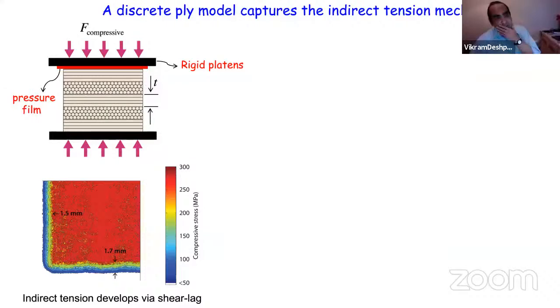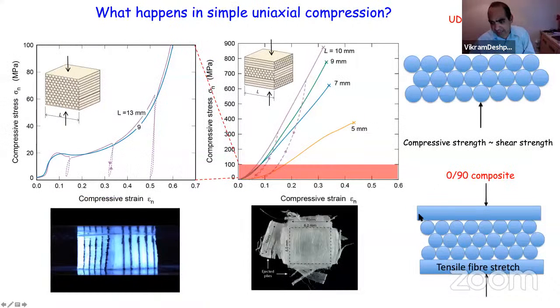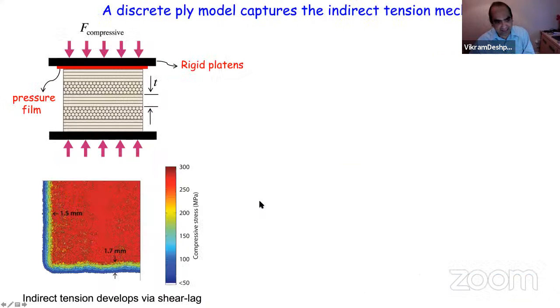We can do experiments to understand all this. Of course, to get this kind of behavior, you need to build up a shear lag, and we can measure those shear lags in experiments. We put a pressure film here, and we can actually measure the length over which that shear lag develops, and you develop that kind of indirect tension.